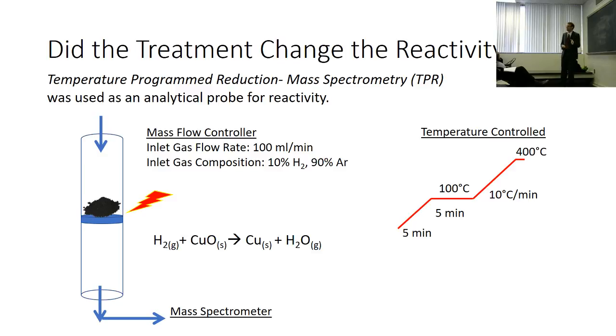Depending on what temperature, you can see how reactive your material is. So I use mass spectrometry. This is measuring the content of your outlet gas based on the mass of the different components, mass to charge ratio, so you can piece out what's there.